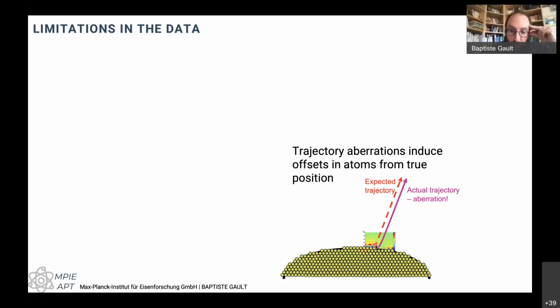And so instead of having this atom right there from the edge being projected along this straight line, it might roll up a little bit to the side, or it might roll up on its neighbor before leaving. There are multiple paths for the ion to leave, which means that when we detect it, and we reverse project it afterwards, we might not position it back to where it really was, but slightly sideways.